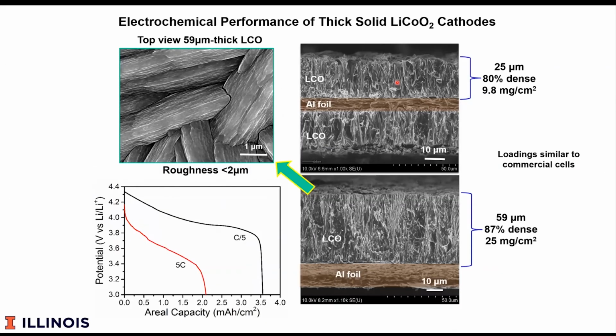Those electrodes I showed so far were a little bit thin relative to commercial systems, so we needed to explore what happens. A typical commercial electrode, as I said, is 50 to 100 microns thick. Here's one that is 60 microns thick. This is 87% dense, so it has about 13% porosity, versus say 30% in a commercial system. And even when charged and discharged in the order of 10 to 12 minutes, it still releases a significant fraction of the stored energy. I'll talk more about that quantitatively.